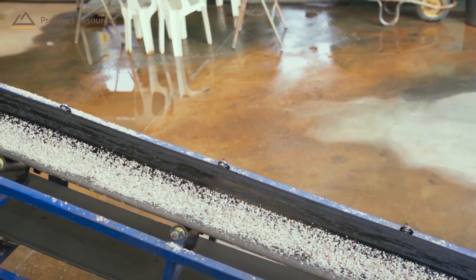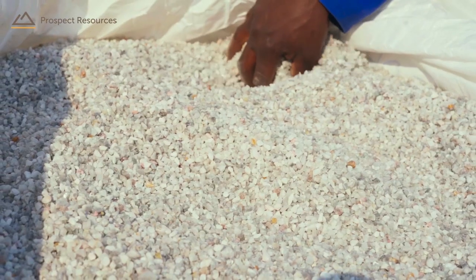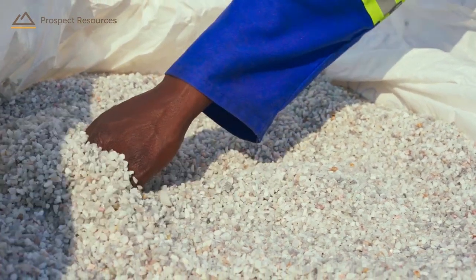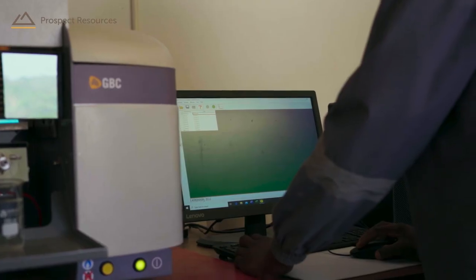The cleaner run involves the rougher concentrate being fed into the plant and the output is the final ultra-low iron petalite concentrate. Each bag is sampled professionally, with samples initially assayed on site, and if spec has been achieved, the bag is then sealed and check samples are sent to the independent accredited assay laboratory.